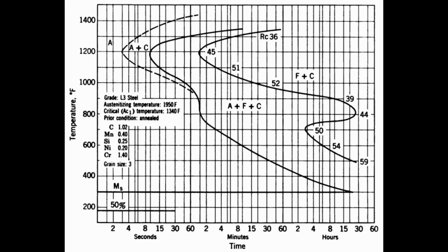So, in this case, the martensite start, where it was close to 500 degrees Fahrenheit with the 52100 from 1550, now it's around 300 degrees Fahrenheit with the high austenitizing temperature. So more carbide was dissolved, putting more carbon and chromium and other alloying elements in solution. All of those reduce the martensite start temperature. So now we can austemper at lower temperatures.